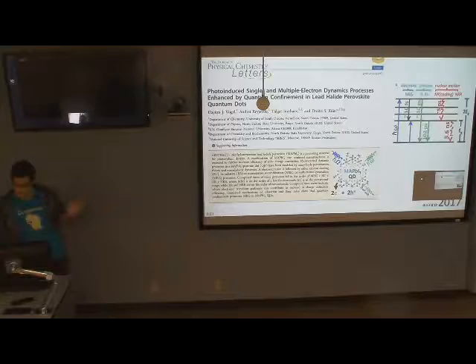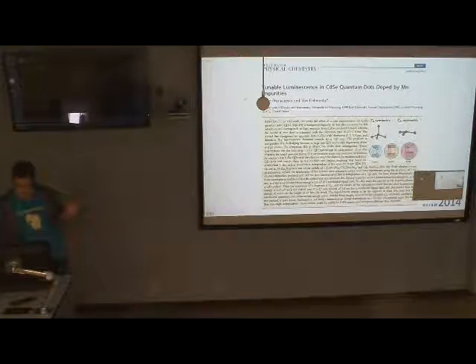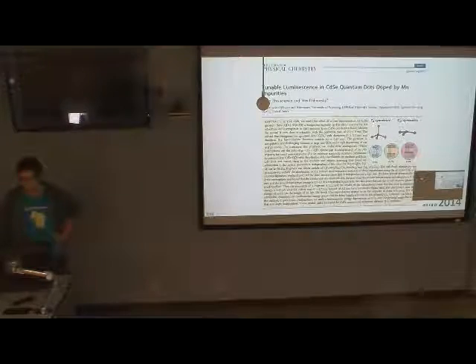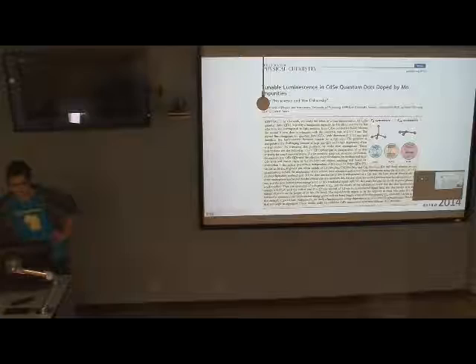Yeah, that's a paper on modeling perovskite quantum dots. And there was one paper I came across by Yuri Danovsky. Is that how you pronounce his last name? Close enough. He modeled the luminescence of Mn dopants in cadmium selenide quantum dots. But in this paper, he didn't actually compute radiative rates or non-radiative rates. He used some theorems to show that if you change the size of your quantum dot, the Mn state is going to go away at some point, so you're not going to see emission above a certain diameter of the quantum dot. That was one of the big things he looked at, and he also did some work looking at the ligand field splitting in these systems. And this is really the only paper I've seen for people trying to model this.